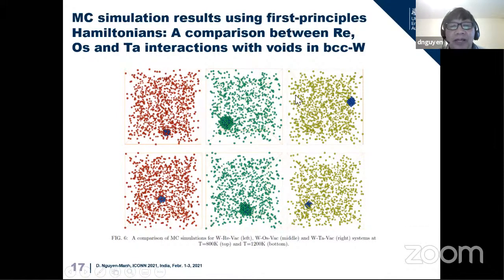Okay, and we can see that at 800K or even at higher, 1,200K, we see the void formation in our Monte Carlo simulation. Most importantly, we see that rhenium can be correlated with vacancy in the vacancy cluster, and osmium is also strongly decorated with vacancy, whereas tantalum is not decorated. So we see a different picture for the three different solute elements.